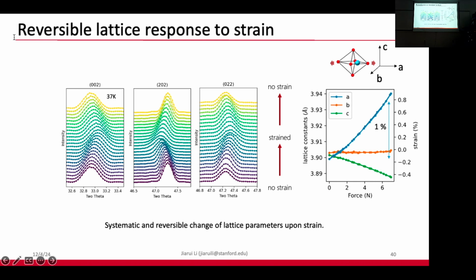This is very interesting because normally this kind of material is ceramic and brittle. Like your dish plates, when you drop them on the floor, they tend to just shatter. And so does this material. When we synthesize them in bulk form, they are very brittle and they tend to break at about 0.1% of strain. But when we get them down to this thin, we are able to stretch them superelastically beyond 1%. We can even go further. There are publications suggesting that it can go up to 5 to 8%, but they're not reversible at that point.